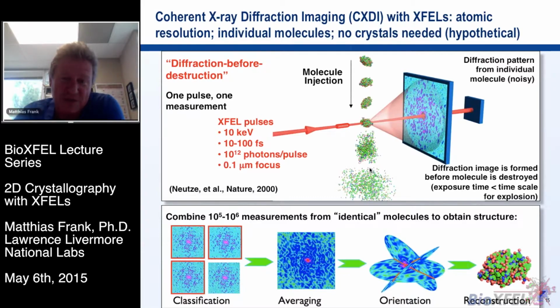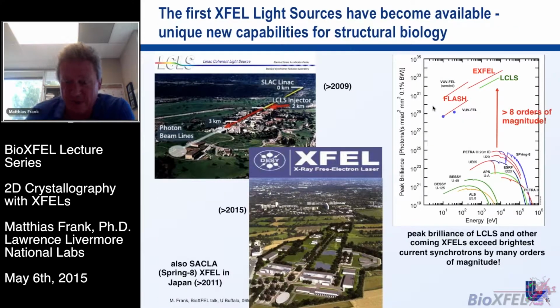But the explosion process, they speculated, could be slow enough that if the X-ray pulse was fast enough, let's say 10 femtoseconds or 100 femtoseconds, a measurable diffraction signal could be produced from a single molecule before the molecule actually flew apart. They did some simulations in that paper and discussed how one could go about getting a structure. Of course, one molecule would produce only a weak pattern, so you have to measure identical molecules many times, like 100,000 or 1 million times. And then there's some classification, averaging, and orientation before you can do a reconstruction.